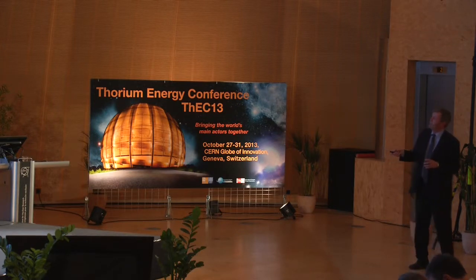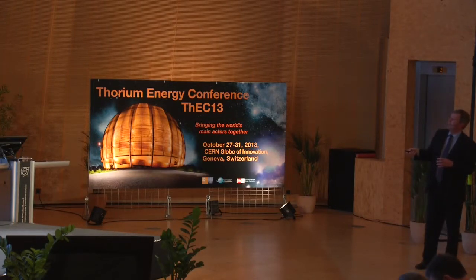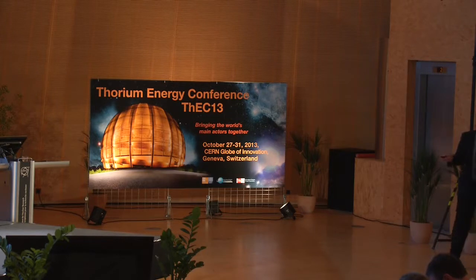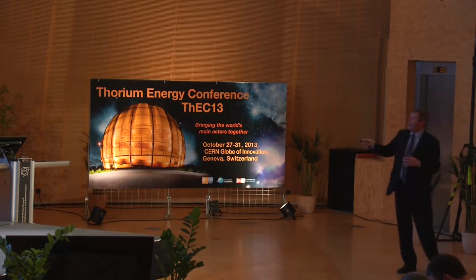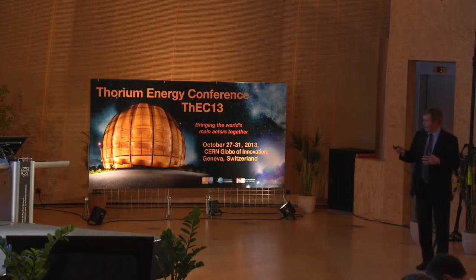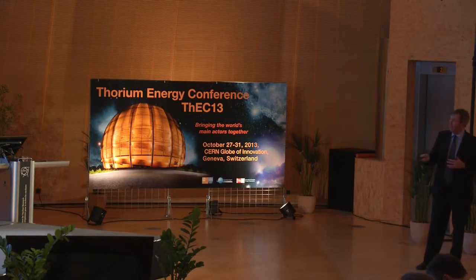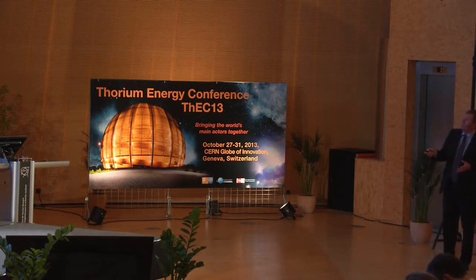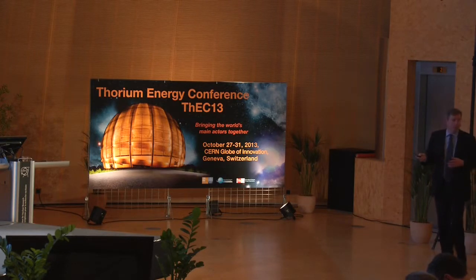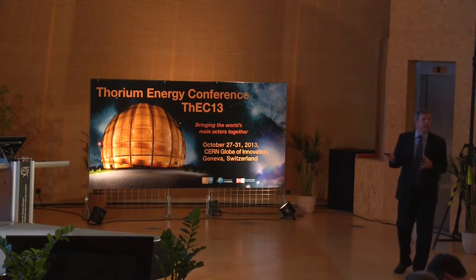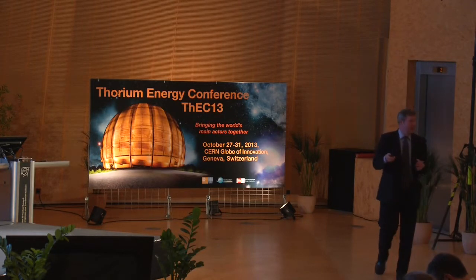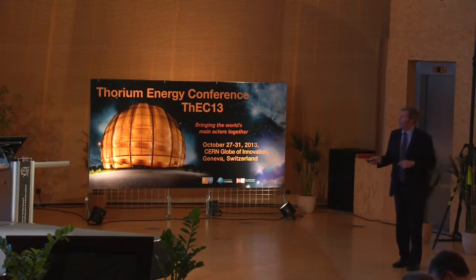But when you change the composition, increasing the beryllium fluoride content, you can see that this network-like structure becomes more developed. So it doesn't take much imagination to imagine that because you've got all of these tie lines flowing through your fluid, the viscosity of this system would be much higher than this one, and that indeed is the case. This is a comparison of the viscosity of the FLiBe system obtained in experiments. That's Oak Ridge data, and these are predictions from our simulation models, and you can see they agree quite closely, and that increase of the viscosity is very much connected with that interconnectedness of the coordination tetrahedra.